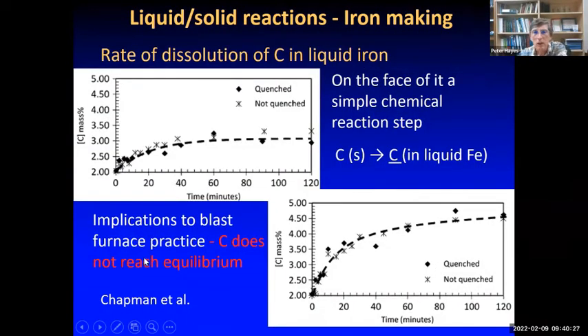I'll take another example here, the last example, which shows that something strange happens when you have heterogeneous reactions. This is some work by Chapman et al. from Wollongong, and they were simply looking at the dissolution of solid carbon into liquid iron as a function of time. So you can see the concentration of carbon as a function of time. We expect a fast reaction rate. We expect it to slow down as we come to equilibrium, but unfortunately, it slows down and actually stops. So equilibrium is somewhere around 4% at this temperature. And over here, this is at a higher temperature. I'm sorry, the temperature is missing from here. I think this is about 1450. This is about 1500 or 1550. So a higher equilibrium, but we don't get there because the reaction actually stops.